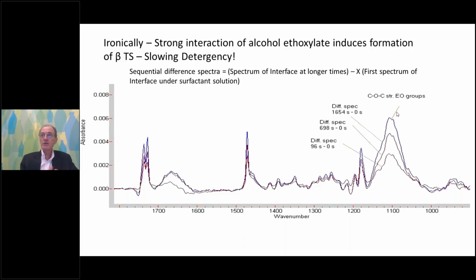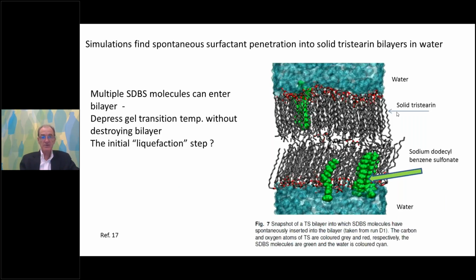So ironically, our initial attack of the surfactant generates the hardest to remove form of the tristearin, and the detergency shuts down. There's actually been some simulation work on tristearin bilayers dispersed in water interacting with good old sodium dodecylbenzene sulfonate as a surfactant, SDBS. And what those simulations show is SDBS can also intercalate into those tristearin bilayers without completely disrupting them, but it will disrupt the crystal structure enough such that the gel transition temperature is lowered. And this seems to be related to the same phenomenon we're seeing in infrared. That is, this partial initial liquefaction step can occur without destroying the entire bilayer.